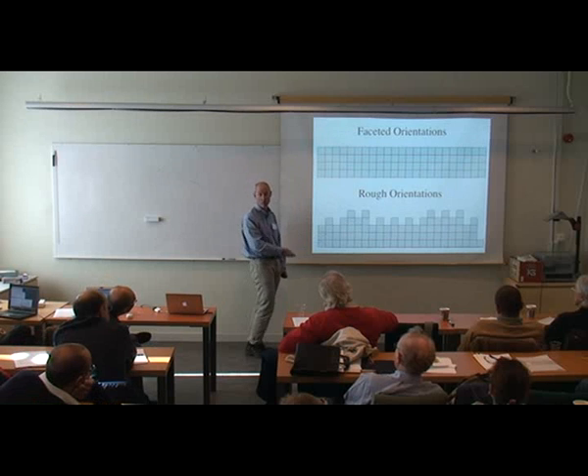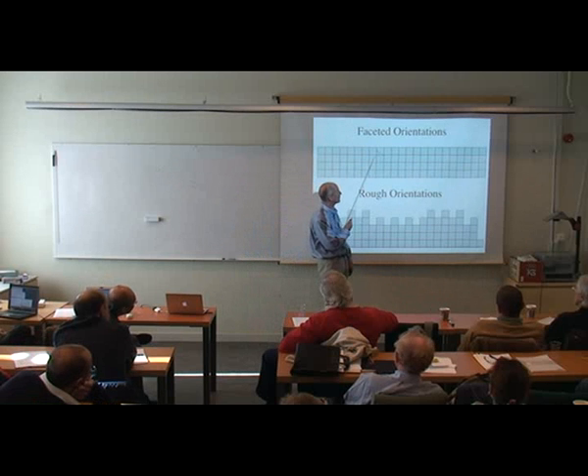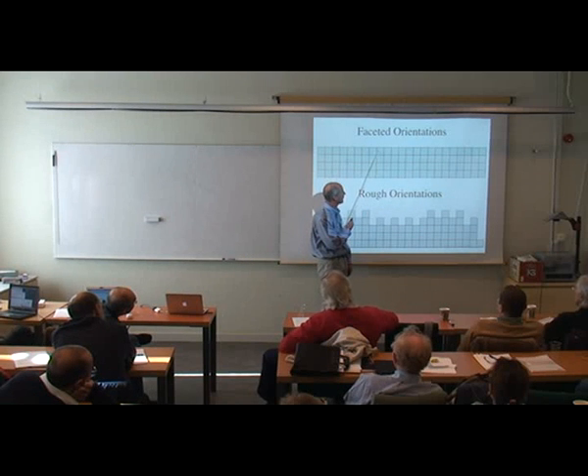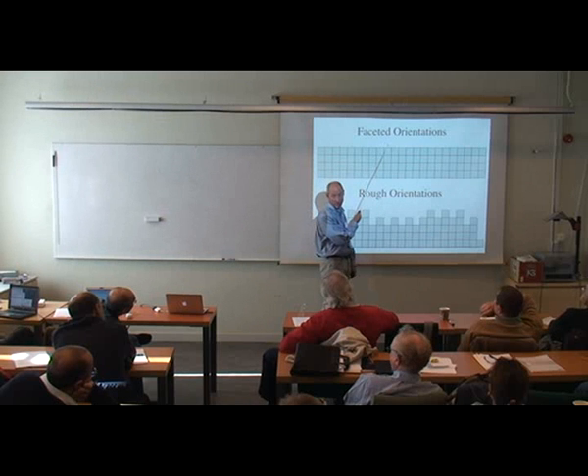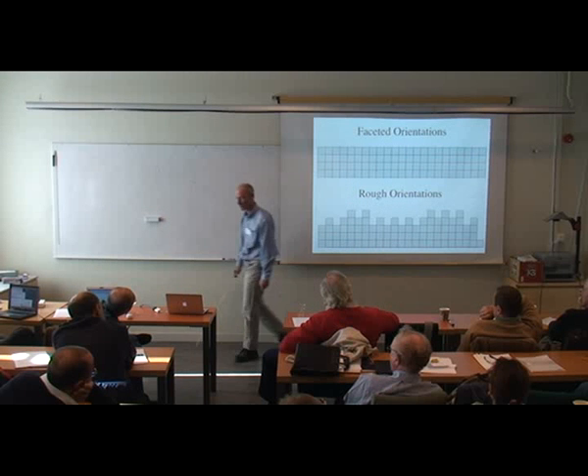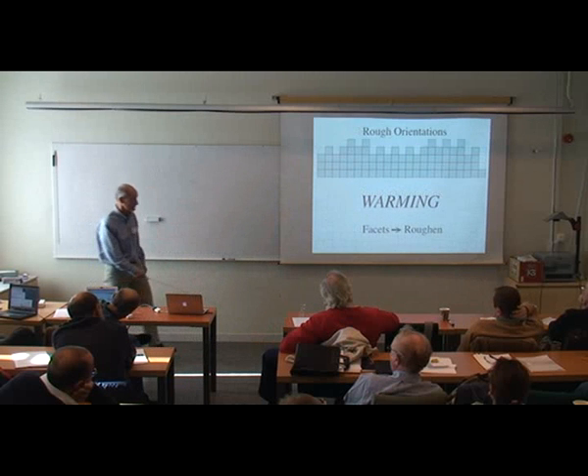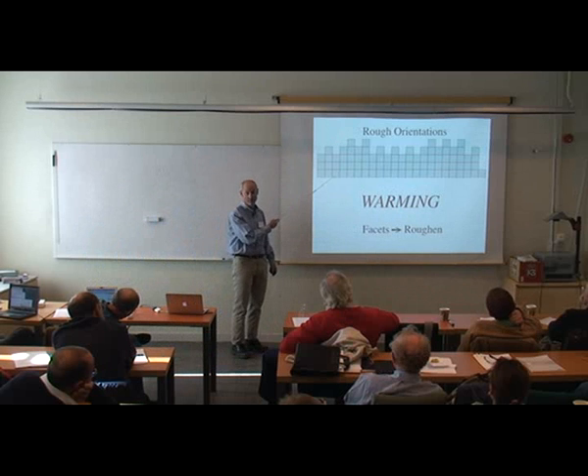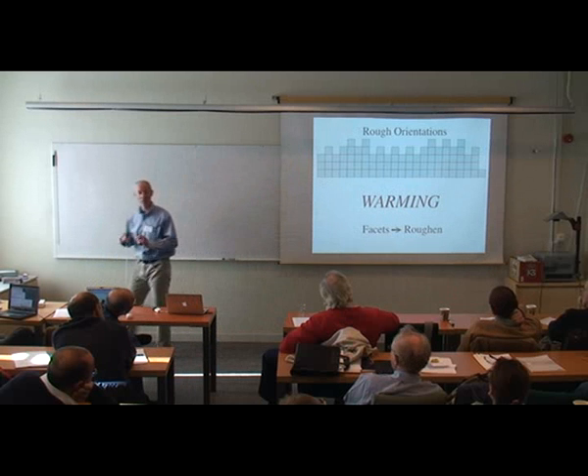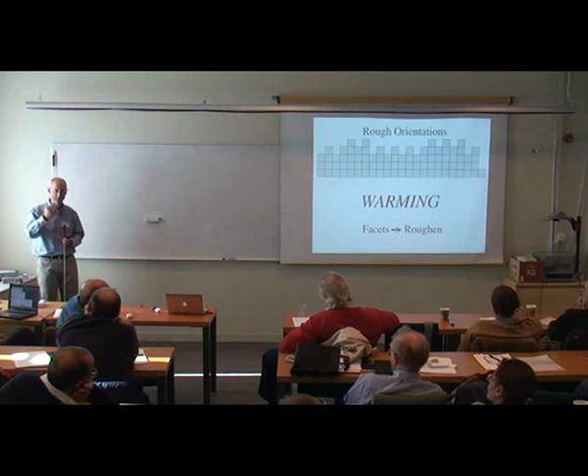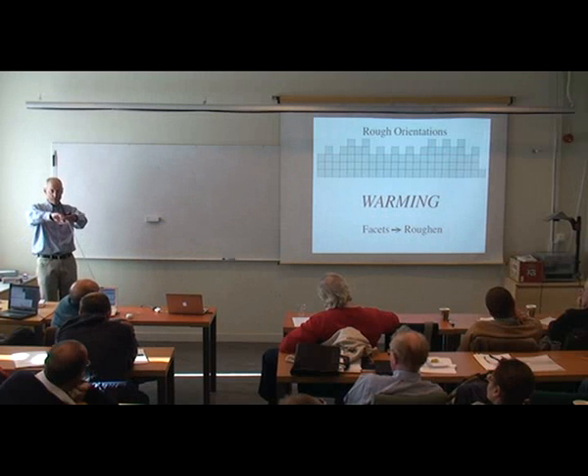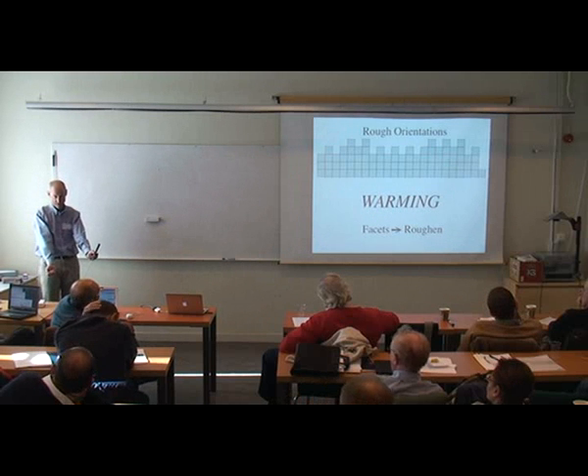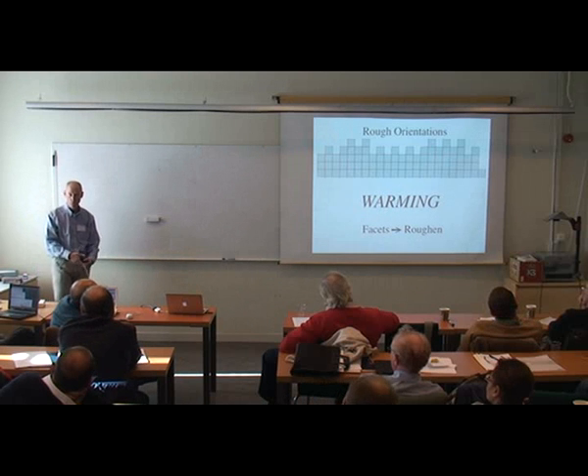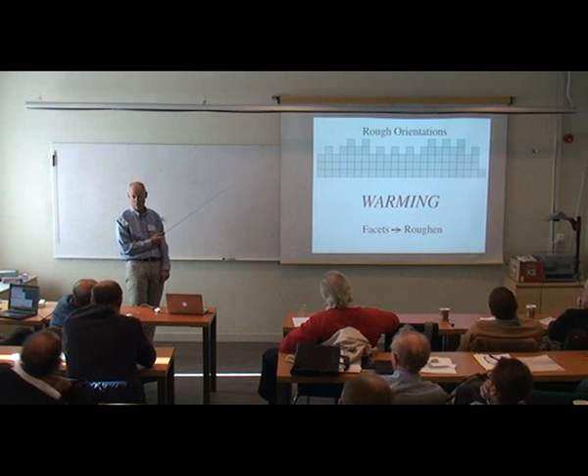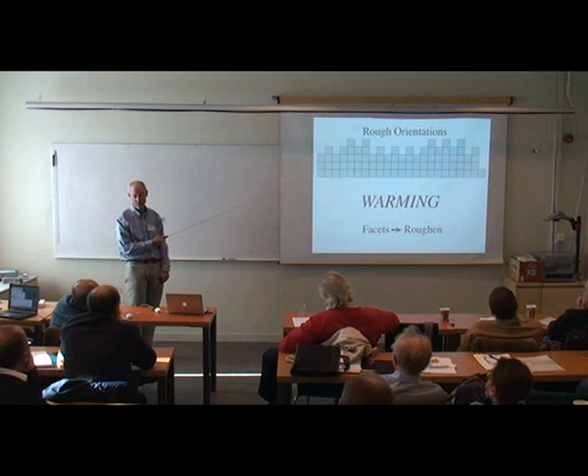So the idea there is that I raise the temperature. See, at absolute zero, I had to do a lot of work against the enthalpy of fusion to put this atom on the surface, right? But I get very little from entropy and configuration. As the temperature rises, entropy wins, and the surface disorders, and a facet can become rough. So that's just the equilibrium state of the surface. Now it's important in thinking about that, both in equilibrium, what it does to change the underlying surface free energy and the surface stiffness, and therefore the shape, but it's also really important to think about what happens to a molecule or atom when it hits these two different types of surfaces.